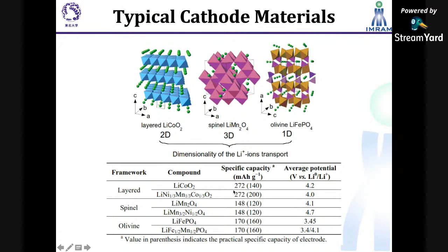And this table shows the specific capacity. The theoretical specific capacity of lithium cobalt oxide, calculated from the energy band structure, is about 272 milliampere hour per gram. However, the value achieved from lithium cobalt oxide is only 140. So only 50% of the specific capacity has been achieved from lithium cobalt oxide.